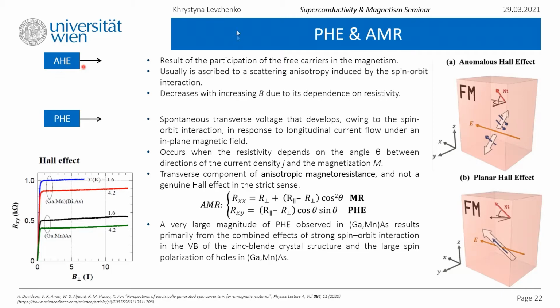And in the end, we have separation of the charge carriers based on their spin direction, spin down or spin up. Like on this image, you may see that the electric field, the spin flow, and the spin direction are all mutually orthogonal. But in the case of the planar Hall effect, magnetization is tilted away from the electric field, but still not perpendicular to it. A charge current forms that flows along the magnetization direction. Since the charge current is spin polarized, the planar Hall effect also gives rise to a spin current.